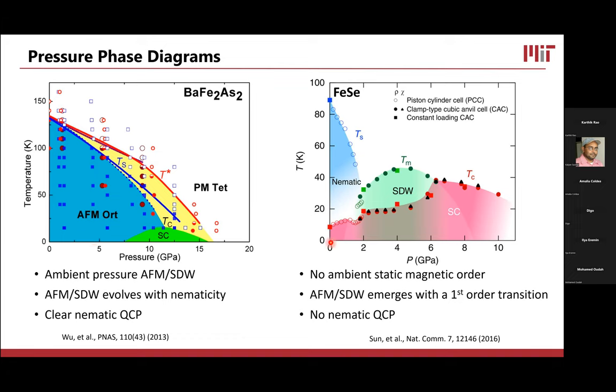So it's not like it's buried here and is a remnant of this nematic order. It seems to have its own dome that lives in this middle range of the pressure phase diagram. And also the superconducting order seems to peak at the high pressure end of this spin density wave dome. And it doesn't really look like there's a nematic quantum critical point at this point.